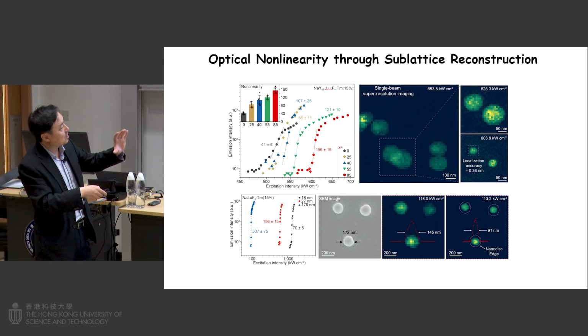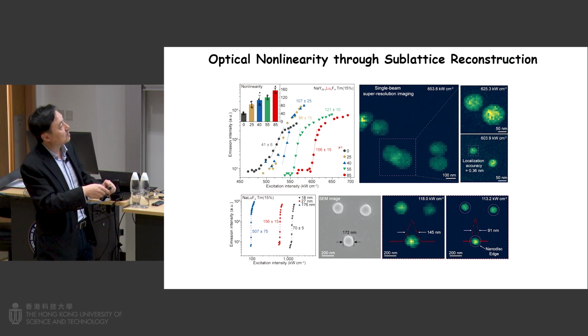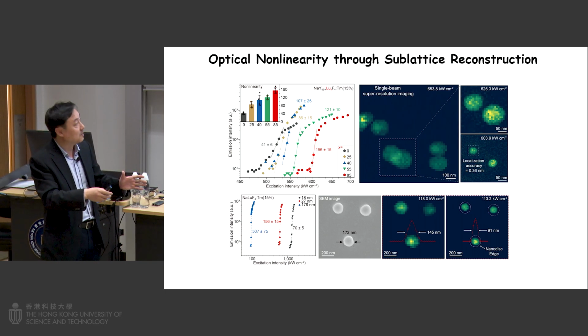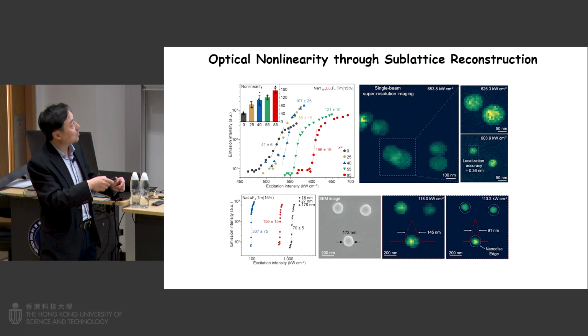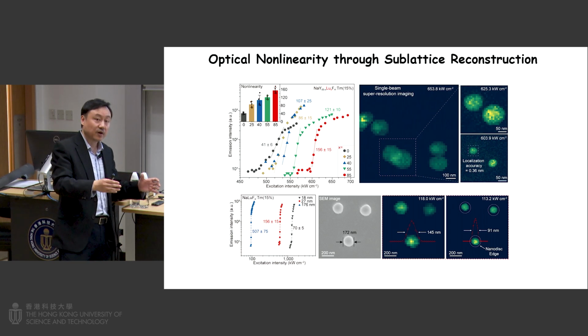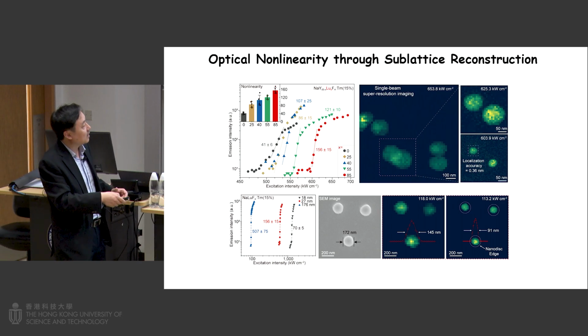Conventional optical microscopy cannot resolve these two particles because of the diffraction limit. But using this, we can clearly resolve the particle distance. You can see we decrease the power, then decrease further. Once we reach the threshold, 603, it becomes very, very clear. So this is quite interesting.